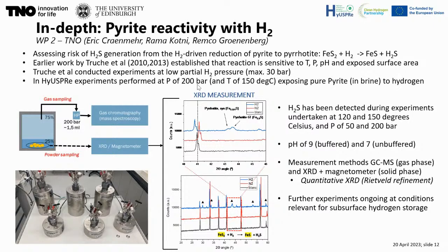If you don't buffer, then the reaction lowers the pH of the formation water or of the brine and would basically self-terminate. But in this case, the measurement with the GCMS and also the XRD shows that this reaction is occurring. This is an XRD result here showing, by the triangles, that specific peaks in the XRD signal indicate that the pyrrhotite mineral is also present here in the post-mortem solid residue. So work in progress. I think we'll probably finish this work by end of September and publish that on the website as well. Still quite a bit to do there.